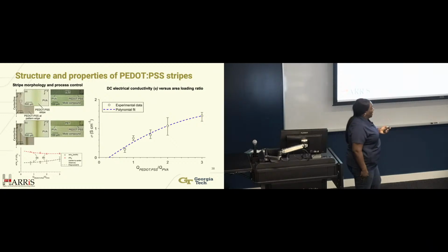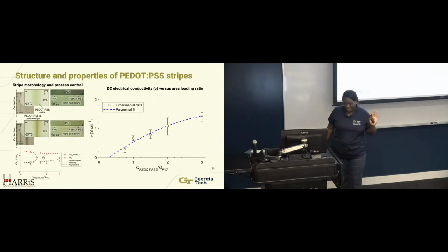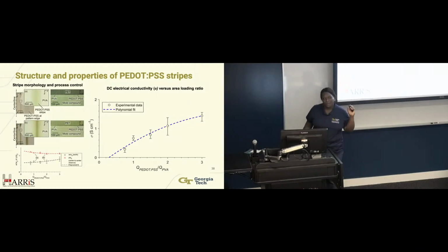But what we needed to know is, will we get some kind of conductivity out? And we did. And some in the room who's in this field, you may say, but that's low, but not technically. We did nothing to the PEDOT:PSS except use it. And we did not alter the substrate, which in this case I believe is PET, which means we took a material that's non-wetting and coated it in a way where we got distinct lines and a readout of like the functionality of that material.